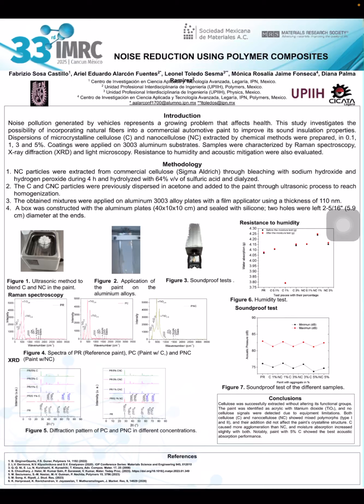So, how did we prepare this material? As I said before, we prepared concentrations of C and NC of 0.1%, 1%, 3%, and 5% by weight. The NC particles were extracted from commercial cellulose, Sigma Aldrich, through bleaching with sodium hydroxide and hydrogen peroxide for 4 hours, and hydrolyzed with 64% sulfuric acid and dialyzed.